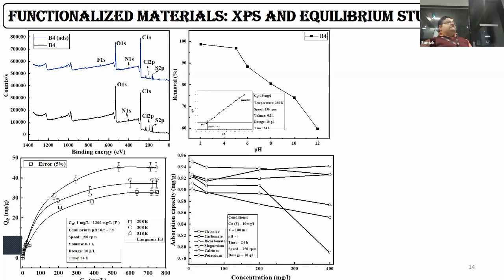Also, we carried out analysis with the effect of different coexisting ions like chlorine, carbonate, bicarbonate, magnesium, calcium, and potassium. The reason for choosing these is that such coexisting ions are present in abundance in normal groundwater. We were able to see that the maximum coexisting effect is shown by potassium. This is because potassium being a positive ion, when the surface of the bead is negative, it starts attracting the positive potassium ions.